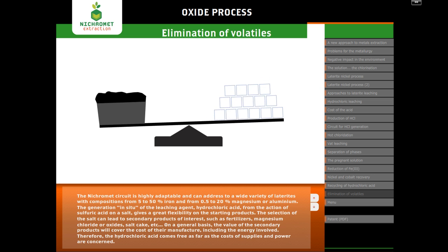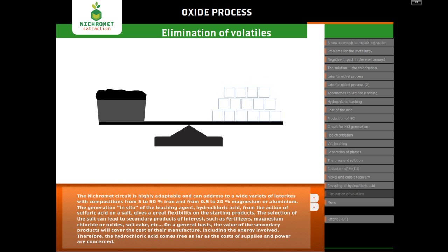The Nichromet circuit is highly adaptable and can address a wide variety of laterites with compositions from 5 to 50% iron and from 0.5 to 20% magnesium or aluminium. The generation in situ of the leaching agent, hydrochloric acid, from the action of sulfuric acid on a salt gives a great flexibility on the starting products. The selection of the salt can lead to secondary products of interest, such as fertilizers, magnesium chloride or oxides, salt cake, etc. On a general basis, the value of the secondary products will cover the cost of their manufacture, including the energy involved. Therefore, the hydrochloric acid comes free as far as the costs of supplies and power are concerned.